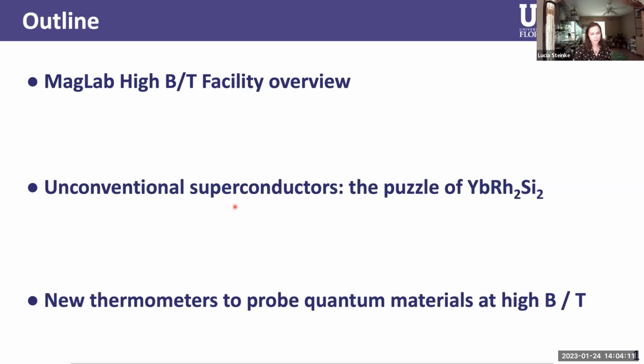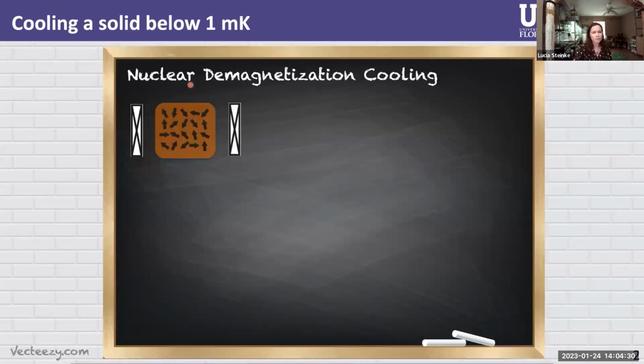So our specialty is really to provide users with two extreme experimental conditions combined: high fields in combination with ultra low temperature of below 1 millikelvin. That's about 10 times colder than the coldest cryostats in the other MagLab facilities. So how do we get our cryostats that cold? We employ a technique called nuclear demagnetization cooling.